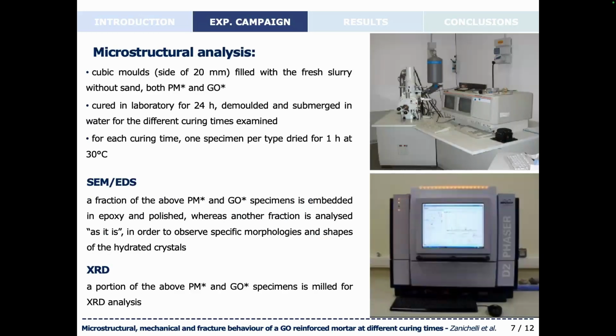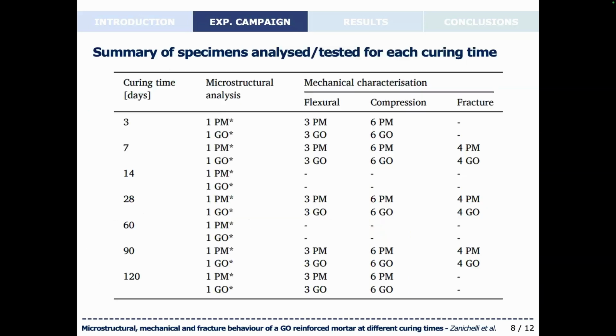Then, as far as the microstructural analysis is concerned, small cubic molds were filled with fresh slurry without sand. That is, as I said before, the PM* and the GO* specimens. Then they were cured in the laboratory for 24 hours, demolded, and submerged in water for the different curing times we have examined. For each curing time considered, 1 specimen per type was dried for 1 hour at a temperature of 30 degrees, and then divided into 2 portions, one to be subjected to the SEM-EDS analysis, and the other one milled for the XRD analysis.